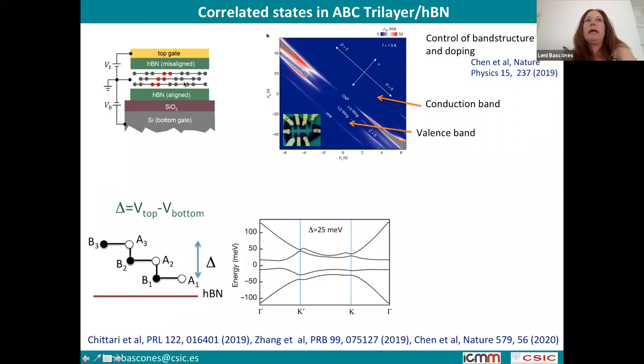So in this system, by applying the two gates, it is possible, as I said, to tune both the doping and the field. In particular, you have here the bottom gate, top gate, and this is a resistivity plot. Moving in this direction, one changes the filling, and moving in this direction, one changes the electric field. Here in this region, one is looking at the conduction band, and here the valence band.